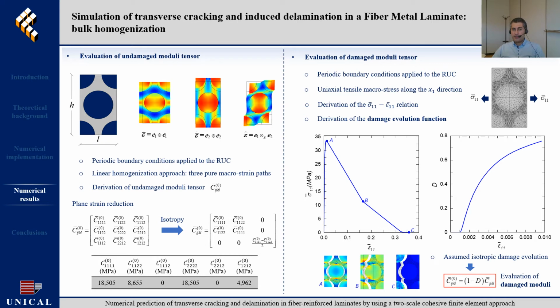Firstly, we present the offline computations performed on a given repeating unit cell to derive the bulk nonlinear response. Here you can find the related numerical outcomes in terms of both undamaged and damaged homogenized moduli tensor. In particular, the damaged moduli are derived by assuming an isotropic damage evolution function, which is directly extracted from the homogenized uniaxial stress-strain curve obtained from the principal path solution.